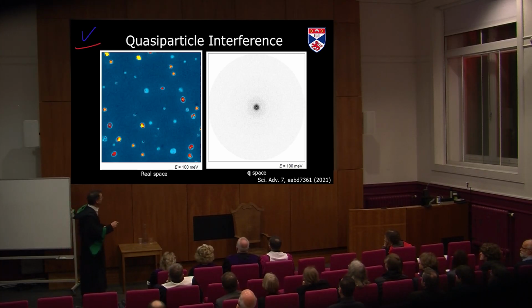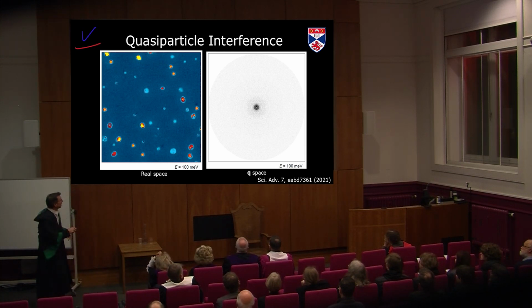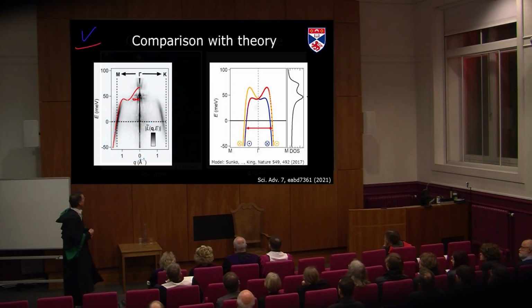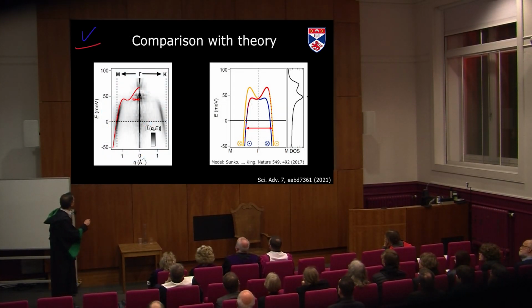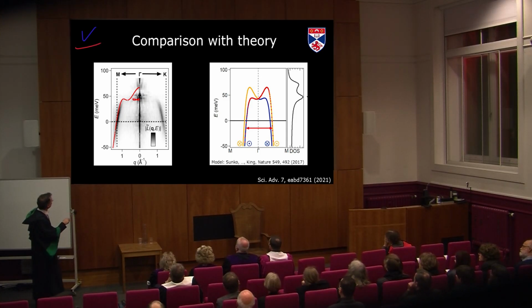And on the right is again this Fourier transformation I mentioned to you. And in the Fourier transformation, when these ripples appear, you can see a big ring appearing here, which moves outwards as the energy goes down. And then we can take a cut through this data set and plot these, analyze them, and compare them to theory. So in this specific case, here's such a cut. You can see this dispersion relation here. Then we can compare that to theory.